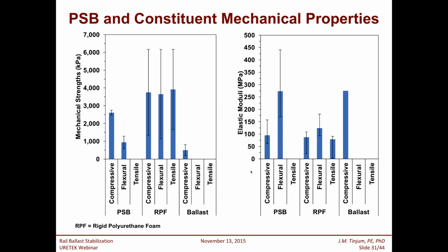In some materials, this should show the polyurethane stabilized ballast in comparison to rigid polyurethane foam in and of itself and ballast. What you're seeing here is that in addition to the compressive strength, we also increase the flexural strength, because clean ballast does not have flexural strength, as it's a granular product without adhesion or cohesion. So we are also increasing the flexural strength, and then going to the right, or excuse me, just more material as far as the elastic modulus, which is just an indication of the repetitious loads to that material as a resilient modulus. So in summary, before we go to our upcoming field project,